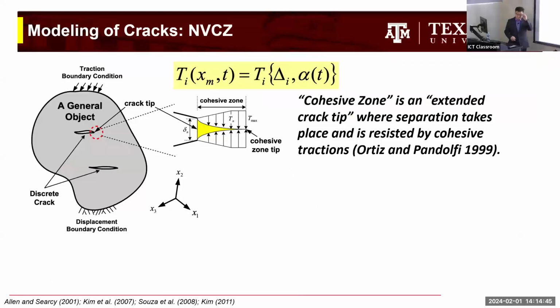I'm talking about fracture, and fracture is one of our primary challenges. I think fracture and cracking in solid mechanics is a very good topic to study. It's very challenging. We are interested in developing a fracture model to better understand and design the mix and structure in our transportation sector. The model we adopted is cohesive zone modeling, which is nothing but an extended, potential crack tip, where the separation is resisted by the cohesive traction. So it's like a constitutive law for a potential crack.